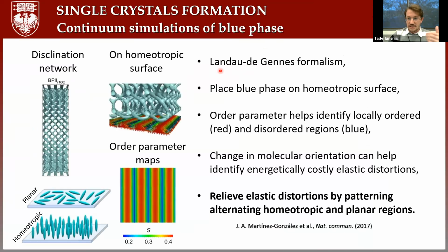Here, let me mention that we typically explore liquid crystals in a liquid crystal chamber or liquid crystal cell. So just imagine we are facing 2 pieces of glass together, and in between are liquid crystals. And continuum simulations of blue phase that are based on the Landau-de Gennes formalism show that if we want to form single crystals in this kind of confinement, then the system prefers that on the surface, the molecules of the liquid crystals are perpendicular to the surface in some regions, and then lay on the surface in others. And again, perpendicular to the surface, lay on the surface.